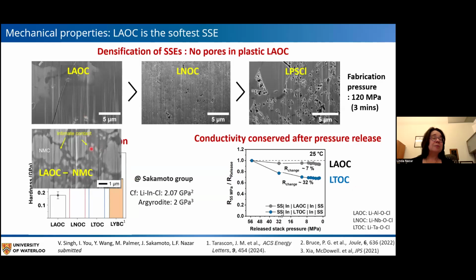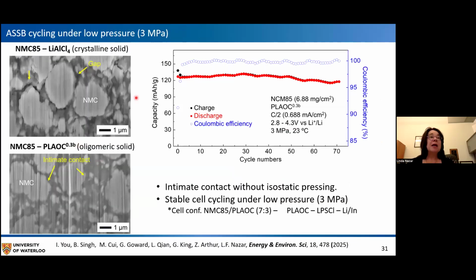And this just shows what a FIB cross-section of the cathode looks like, showing the intimate contact that one has between the LAOC, the viscoplastic solid electrolyte, and the cathode active material. Same picture. And again, this is now at low pressure of 3 megapascals. And you can see that the cycling stability, these don't work quite as well at 3 megapascals as they do with a higher pressure, but it's still, this is without isostatic pressure.